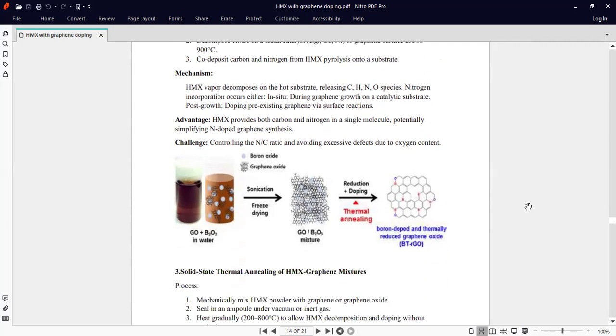Mechanism: HMX vapor decomposes on the hot substrate, releasing carbon, hydrogen, nitrogen, and oxygen species. Nitrogen incorporation occurs either in situ during graphene growth on the catalytic substrate, or by post-growth doping of pre-existing graphene via surface reactions. The advantage of this type of doping is that HMX provides both carbon and nitrogen in a single molecule, potentially simplifying nitrogen-doped graphene synthesis. But the challenge is controlling the nitrogen-carbon ratio and avoiding excessive defects due to oxygen content.